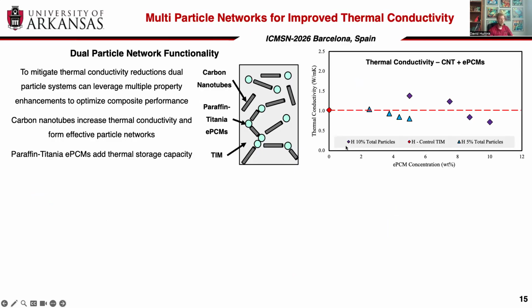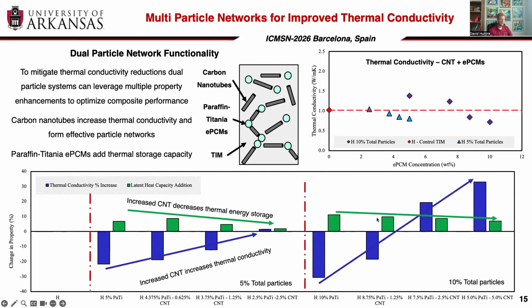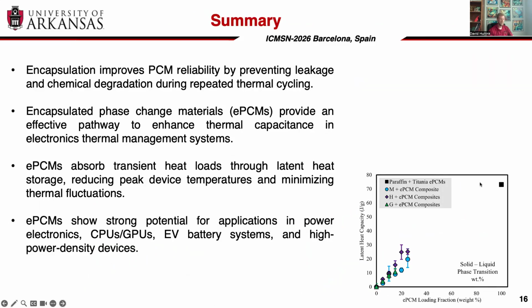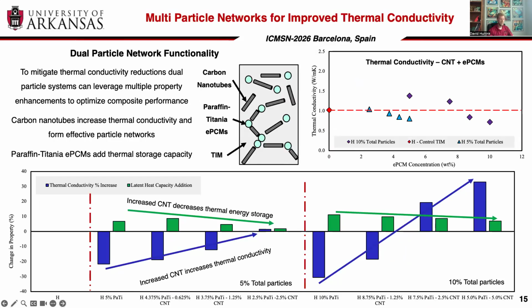So we looked at incorporating carbon nanotubes to effectively raise the overall thermal conductance or counteract the loss that we see from the ePCM particles. So essentially this becomes a balancing act of the loading of ePCM particles, which increase our thermal energy storage, in combination with increasing the thermal conductivity coming from the carbon nanotube. So there are some sweet spots that can be found in that optimization.